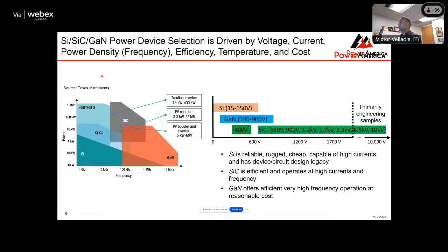So therefore, if you look at this graph right here, you will see that silicon carbide basically is available at 650, 900, 1.2 kV, 1.7, and 3.3 kV. And these are all products that are available on the market today, while 6.5 and 10 kV devices have been successfully demonstrated. If you look at gallium nitride, it's available in the 100 to 900 volts with some recent results at 1200 volts and even 1700 volts. And of course, silicon is extremely competitive up to 600 volts. So silicon is reliable, it's very rugged, it's very cheap, it's capable of operating at high currents, and there's design legacy, meaning people know how to design with silicon.